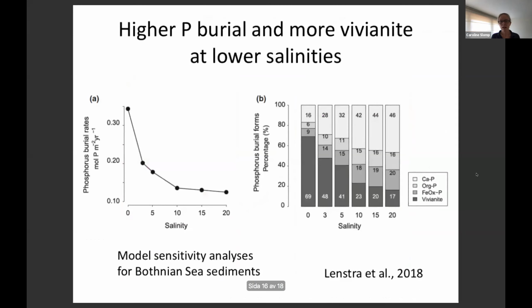Next slide, please. Now, you can then try to develop scenarios to explain this, and we've done that in modeling, but we also did some sensitivity analysis with a reactive transport model. In that model, you describe all the processes that occur in the sediment. And then we looked at the effect of salinity. If you change the salinity, what you can see in these graphs is that if the salinity is lower, you get more Vivianite formation and more phosphorus burial. And the higher the salinity, the less phosphorus burial, the less Vivianite formation. That's what you see here on the left-hand side, phosphorus burial rates as a function of salinity, and on the right-hand side, phosphorus burial forms as a function of salinity.